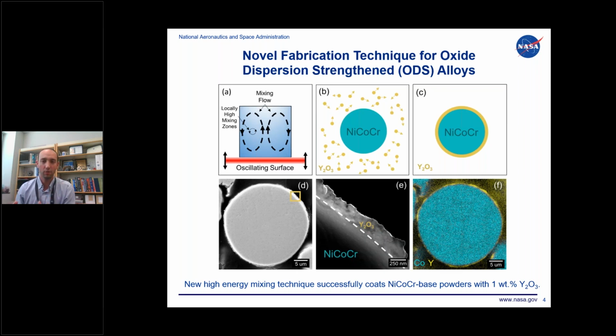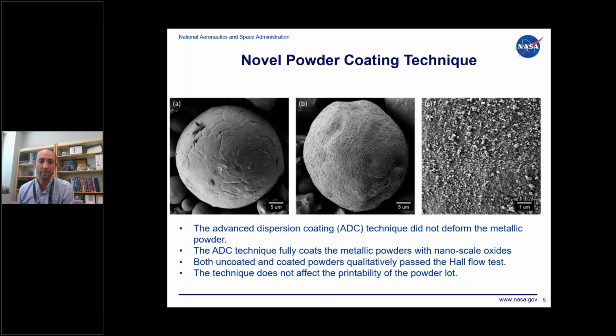So we took this nickel, cobalt, chrome powder and nanoscale yttria particles, and we would mix it in these resonant acoustic mixers. What happened was those nanoscale oxides would adhere and coat the metallic nickel, cobalt, chrome powder. You can see some SEM images on the bottom here, and if you look at the thickness of this type of coating, it's about 250 nanometers thick, roughly, that would get adhered to the metallic powders.